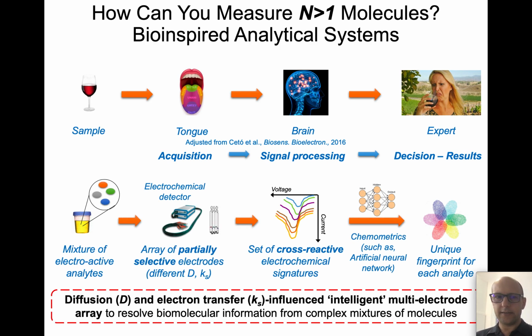So our approach is using an array, to differentiate or quantify multiple redox molecules directly in the biofluid by using an array of electrodes modified with different modifications, generating data that are now partially selective to the different molecules we have in our sample. They will generate a set of cross-reactive electrochemical signatures, and we use chemometrics or machine learning algorithms to identify a specific fingerprint for each one of the molecules. And now by measuring the samples, we can directly quantify the levels of the molecules by using the different models.